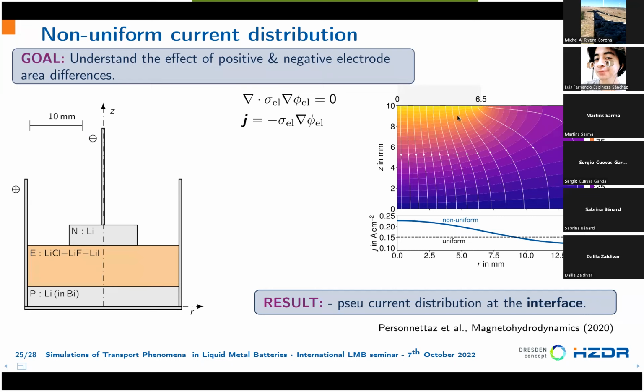And this is the result. So this is the electrolyte layer. We assume uniform potential at the top and bottom interface, and the white lines that we see here are the current lines. And so we have this blue line as a current distribution that is different from the uniform one that we have assumed until now.